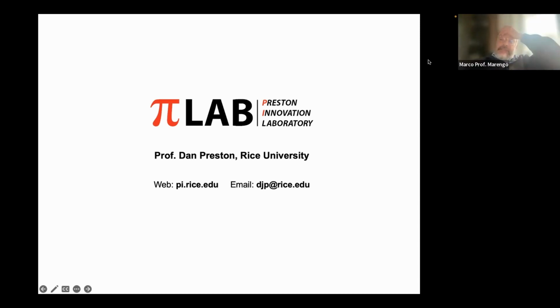And the other thing is about the boiling. As you know, we just published a paper in Nature Communications about the nanoscale origins of boiling. And theoretically, we saw that a very small variation of wettability in one spot at the nanoscale is enough to change the situation completely. So contamination really can be interesting. In the case of the experiments with the CHF, with the silicon wafer and so on, there are two points to make. The first is that we already saw that even a nanocavity, a cavity of the order of 2-3 nanometers, can change the situation.